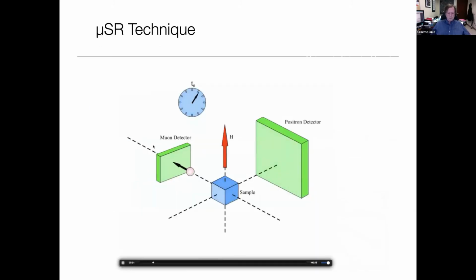So the experiment works like this: a muon comes in, it goes through a detector and starts a clock, and lands in our sample. The spin then precesses under Larmor precession in the local magnetic field until it decays at some time, 2 microseconds later on average. When it decays, the positron goes through another plastic scintillator detector, and we stop the clock at that point, and we make a histogram of detected positrons in some direction as a function of time after implantation. So we do this one muon at a time, and then we build up a decay spectrum like this, which has, of course, the muon lifetime on top of it.